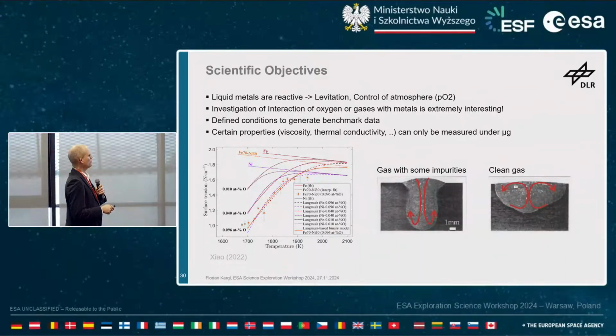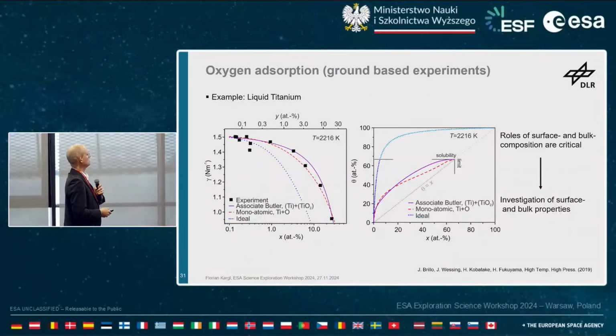From a practical point of view, this can have impact on what is happening in applications like welding. With gas with some impurities, so you have oxygen, Marangoni flow is reverted, and you get this very deep and shallow welds. If you use clean gas, it's getting more broad, fluid flow is changing in this case. So it's interesting really to measure this. So far, there are only ground-based experiments. As I said, the possibility on the space station is upcoming. So this is from liquid titanium.